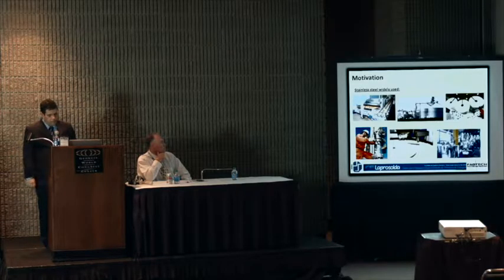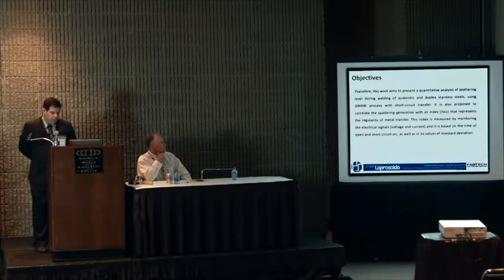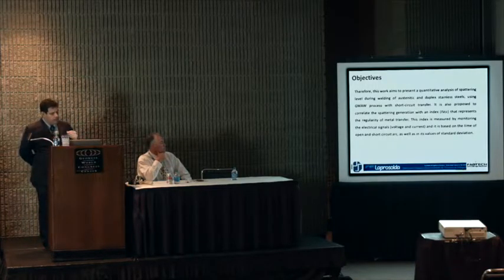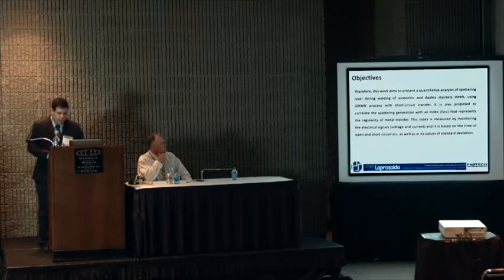Stainless steel is widely used for general applications, so it is definitely a worthwhile material to study. We also present a quantitative analysis of spattering for Austenitic and Duplex stainless steel when welding with short circuit metal transfer in gas metal arc welding. By doing that, we try to present and correlate an index we developed for carbon steel, and in this work we try to do the same for stainless steel. It's called IVCC, an index based on both the open arc and short circuit time periods, and we try to show that this index represents the regularity of metal transfer. Let's see if we can manage to do that. This index comes from the analysis of the electrical signals.